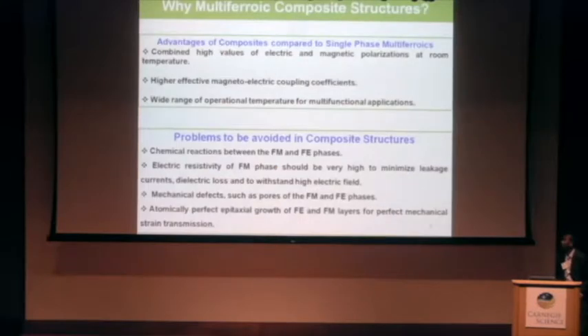composite structures are needed. So why multiferroic composite structures? The advantages are we can get combined high values of electric and magnetic polarization at room temperature, and we get higher effective magnetoelectric coupling coefficients, and we get a wide range of operational temperature for multifunctional applications. We can get both the ferroelectric and ferromagnetic transitions above room temperature.